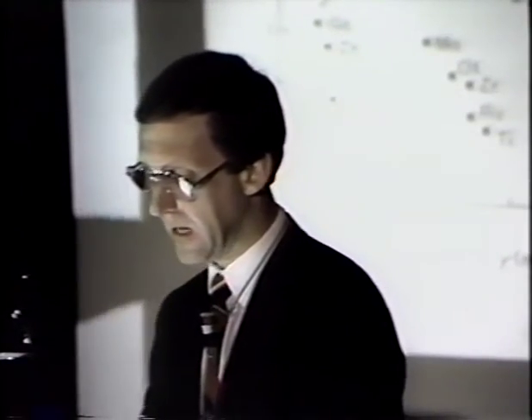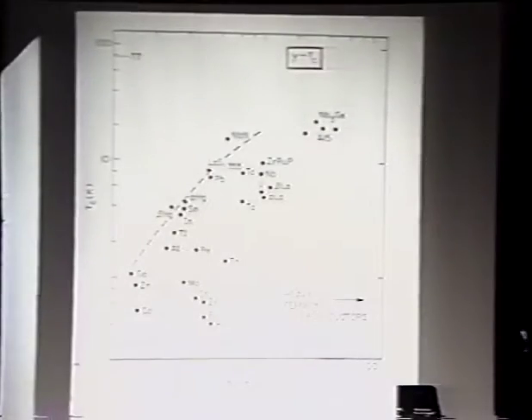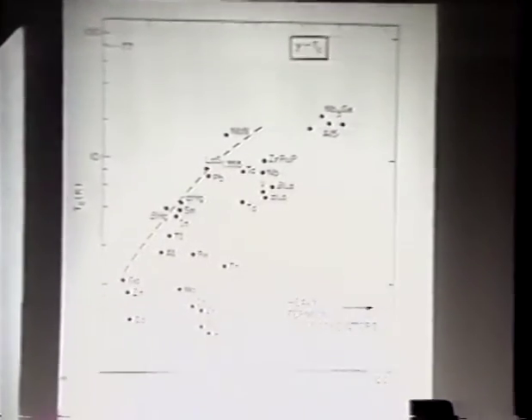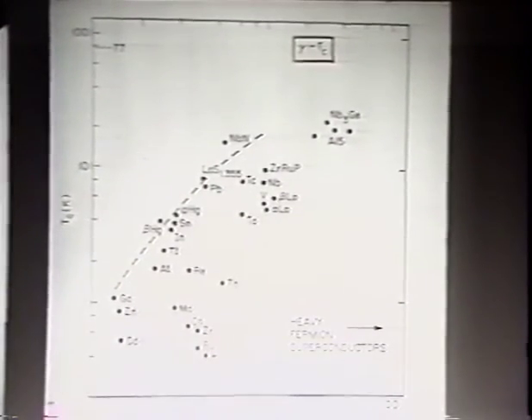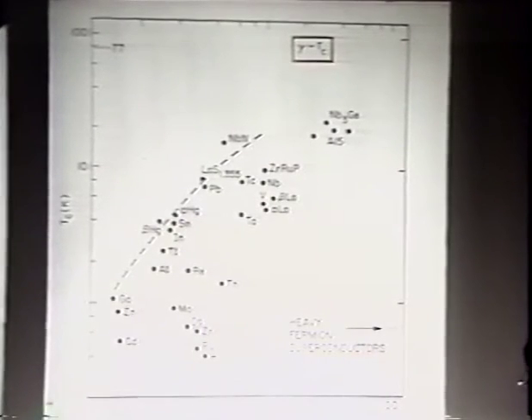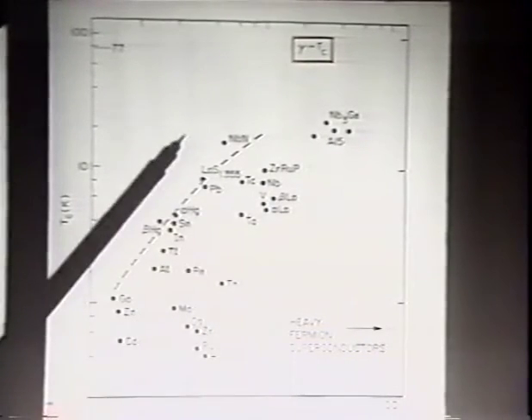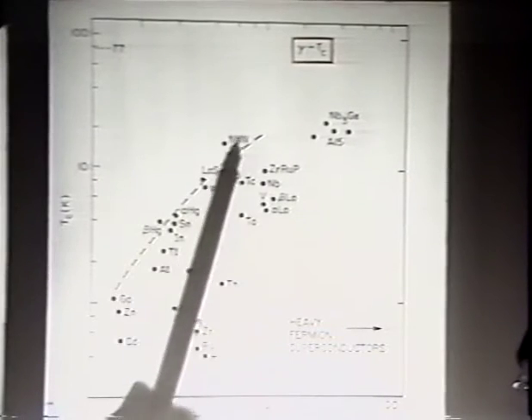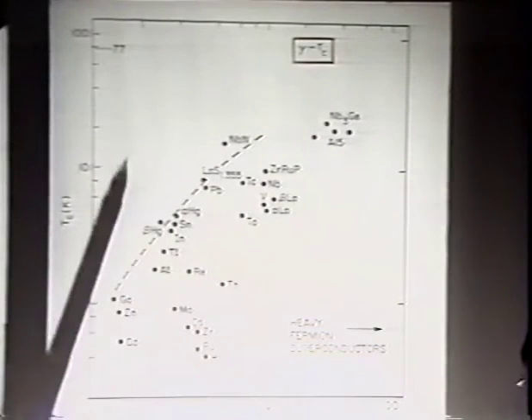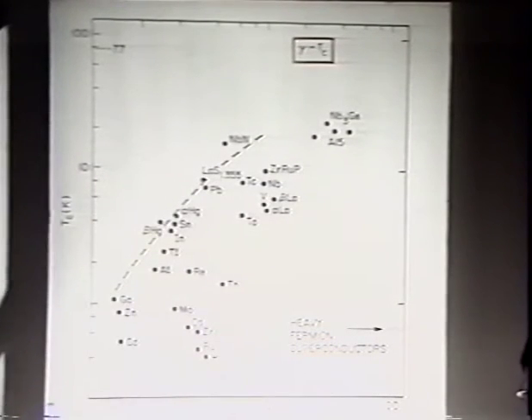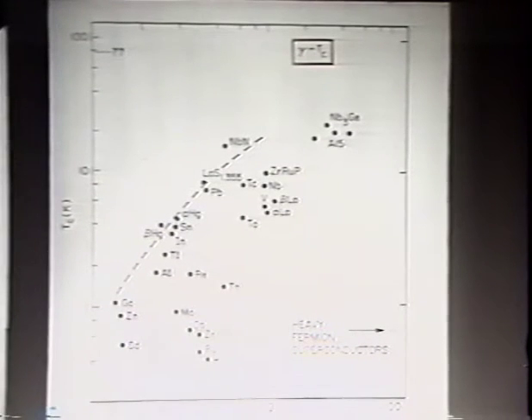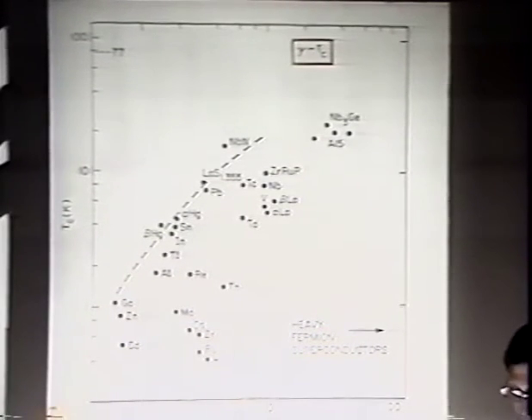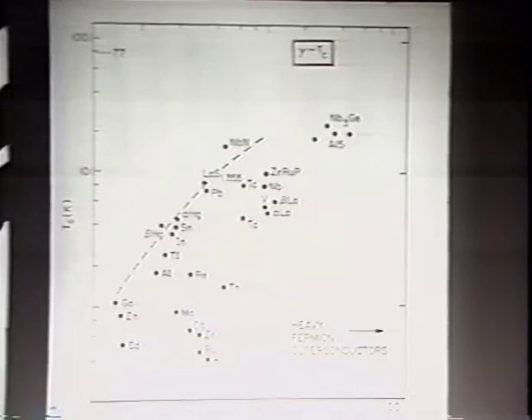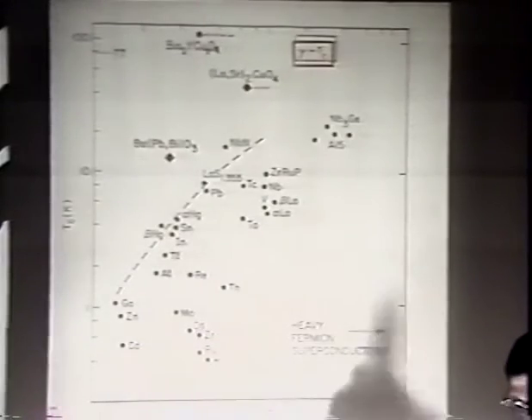Let's come back to superconducting materials here, and I'd like to compare these oxide superconductors with all the rest of the superconductors we know. I hope you find your favorite down here. If not, we can put it on. It will certainly not exceed this line. That's an empirical line beyond which no superconductor has been observed. It's a TC versus gamma plot, on a double logarithmic scale, so we can catch the recent developments here. So if you flip over to our oxide superconductors, that's where they are.